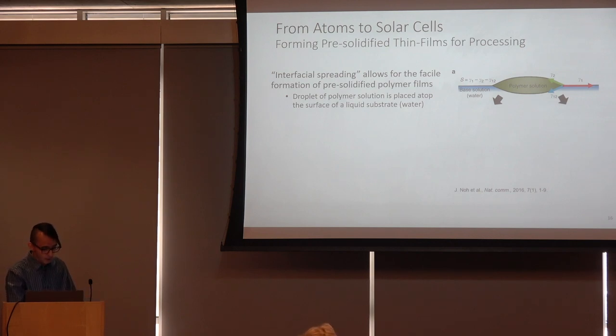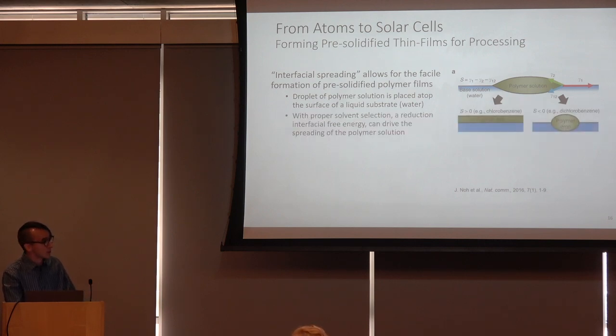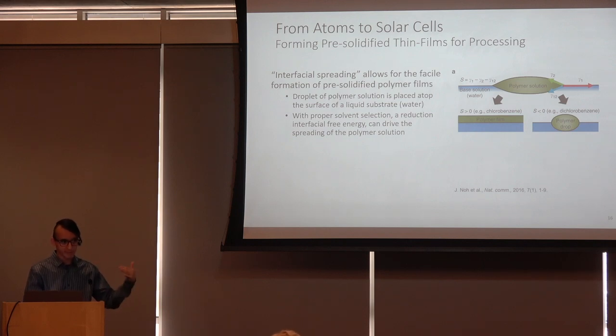Now, the way that it works is you make a solution of polymer, and with appropriate solvent selection, by placing the droplet of polymer on the surface of water, you can get spontaneous spreading of that solution across the surface. And this occurs due to a reduction in the interfacial free energy of the system. Water has a very high surface tension. It's not an energetically favorable surface to exist. And so nature tries to cover it up by some means.